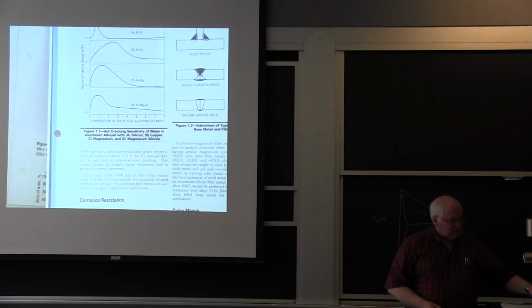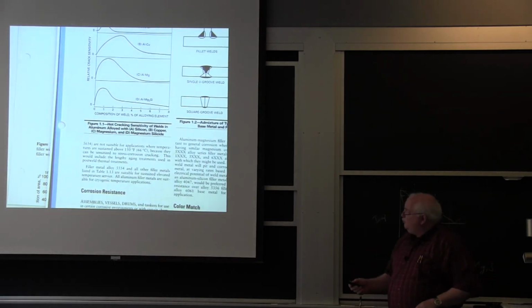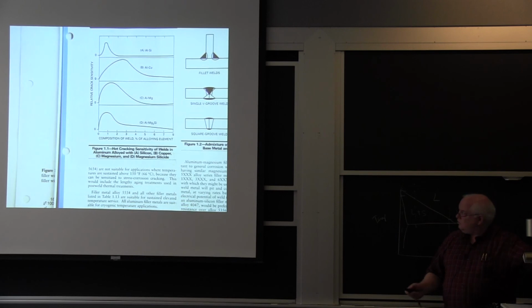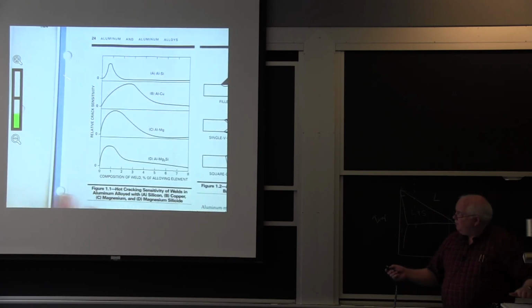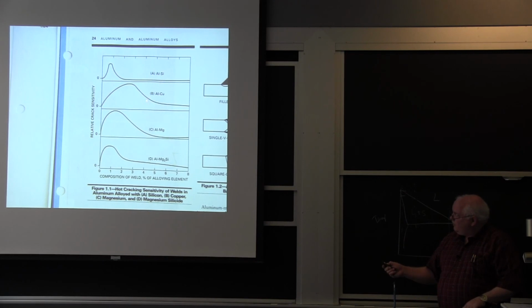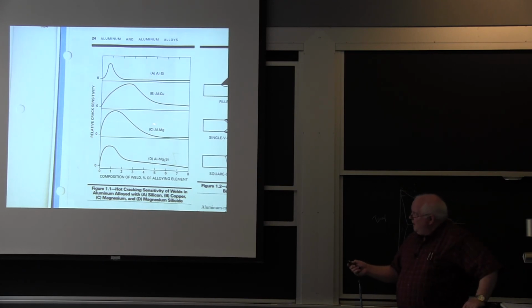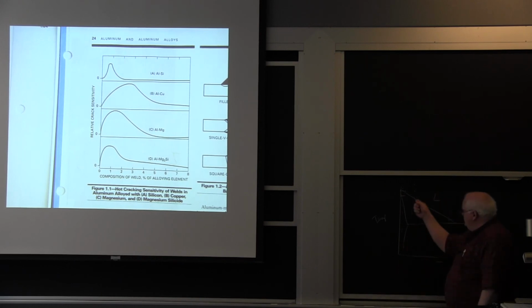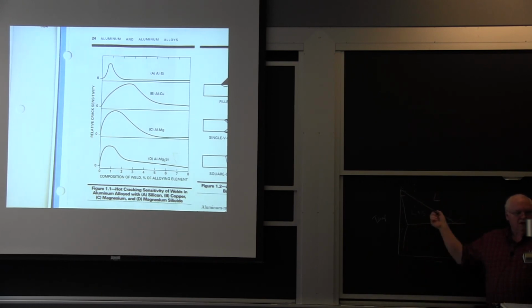So one of the things that you can look at is the freezing range or the composition that causes cracking in a number of different aluminum alloys. So this is aluminum silicon, which is 4000 series. Aluminum copper, which is 2000 series. Aluminum mag is 5000 series, and aluminum mag silicon, which is 6000 series aluminum alloys. And you find that with the composition of the weld, percent of alloying element, you'll get your maximum cracking at some intermediate level. And that's just this wide freezing range. Highly alloyed, no cracking. Lightly alloyed, no cracking. Wide, intermediate, lots of cracking.